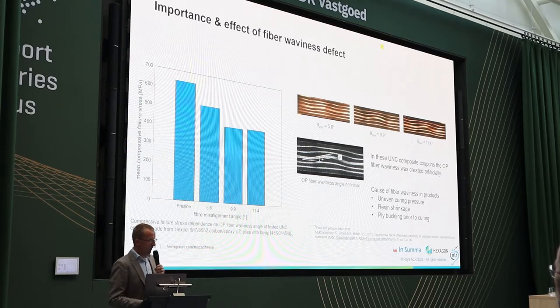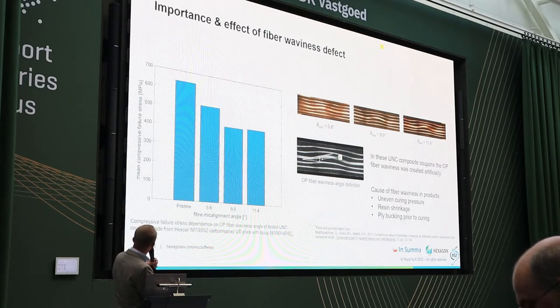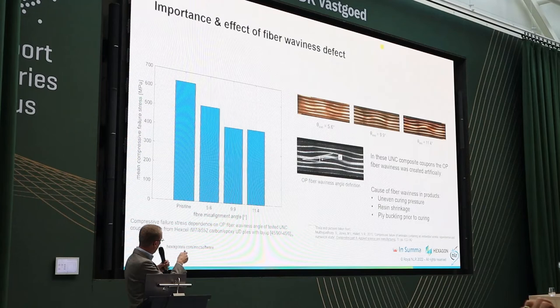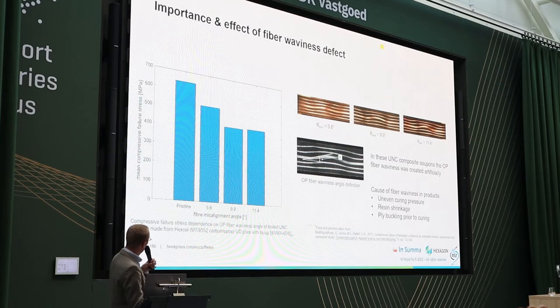First, I looked in literature at other people who also worked on this, and in the left graph you see the compressive strength of unnotched coupons of a carbon epoxy composite. The left bar is a pristine coupon, with more than 600 megapascal compressive strength. But if you have a 5.6 degrees fiber waviness angle, that's the angle with the horizontal plies, let's say, as in the picture on the right, then it drops by more than 100 megapascals. So that also depends on the amplitude, of course, but it's a large decrease of strength and also stiffness, like shown here.